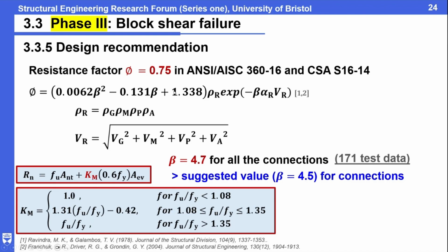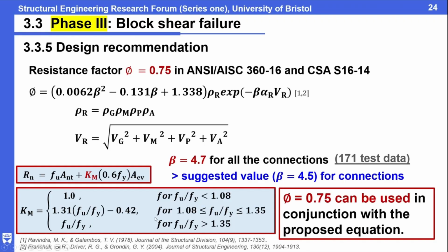So for the North American, we just consider 1 is okay. So here we follow this one, and just check whether the suggested resistance factor phi value of 0.75 can still be used for this proposed equation. The results show that our beta is 4.7, a little bit larger than the suggested one. So it means it is conservative and can still be used. So 0.75 can be used combined with the proposed equation.